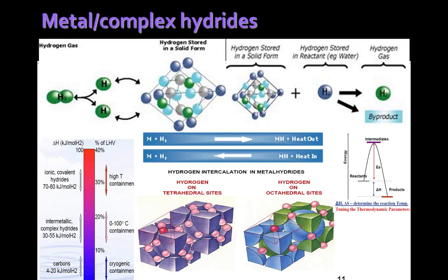In the one underneath, hydrogen intercalation in metal hydrides, you see two types of structures available so far in our crystal systems. Hydrogen could be localized into tetrahedral sites, which means there is a red atom sitting tetrahedrally, or hydrogen could occupy octahedral sites, that is with 6 hydrides. It is just a cross-section, so you can see that the hydrogen could be localized into tetrahedral or octahedral sites.